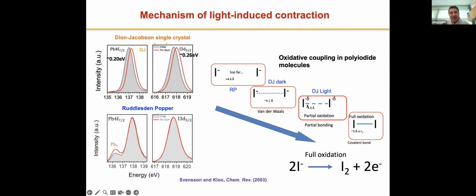Now, when you actually put light on the material, you get a photoexcitation from the iodide antibonding to the lead antibonding orbital. And so you're slightly reducing the negative charge on your iodide. What happens is that you start to get interactions between these two iodide molecules, through a partial sort of oxidative coupling. This is a mechanism that is quite well known in catalysis. So you get this partial bond formation upon light illumination. Then when you take the light away, you restore equilibrium and get back to your original distance of about 4.1 angstrom. Of course, the extreme case of this would be a full oxidation, where these iodines would be so close that they would form a covalent bond. And we are, of course, not in this regime at all.